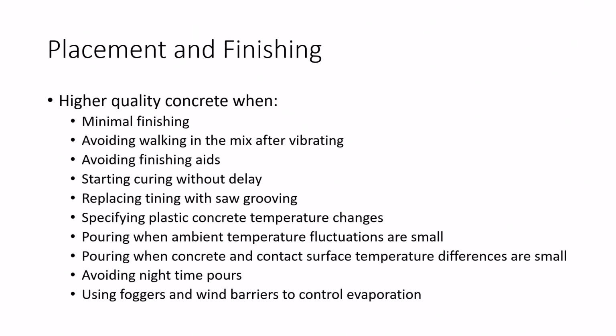So there was some discussion about specifying temperature changes for plastic concrete. So trying to pour when the ambient temperature fluctuations were small, or pouring when concrete and contact surface temperatures are close, so that would be the girders. If the temperature of the concrete and the temperature of the girders were very different at the time of the pour, it seemed like it was causing more trouble. And for the same reason, avoiding night pours. So really controlling that temperature as much as you can seemed to result in better quality concrete.